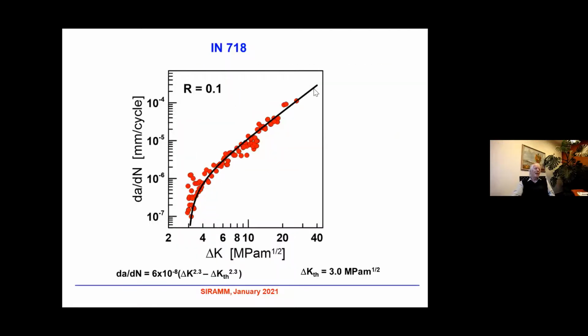And here are results of the measurement of crack growth rate versus stress intensity factor amplitude. What we can see is that the scatter of data is not so bad. We can fit the experimental data by this equation, and the threshold value is nearly 3 megapascal meter to 1/2.